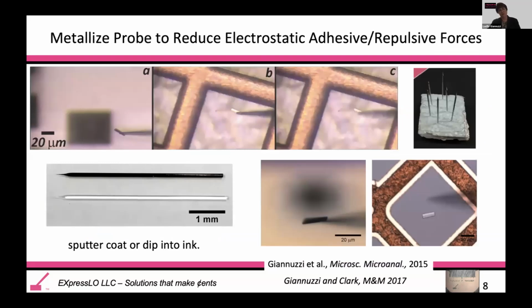We actually learned over the years that it is also beneficial to totally eliminate electrostatic forces, and the way you can do that is to metallize the tip. So we use glass probes that are pulled to a fine point, about a micron in size. And with these tips, we're using the surface area of the rounded edge of the tip. We are not poking at the sample.